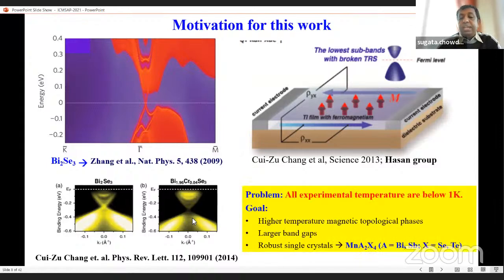The question is that all this experimental work has been done at very low temperature, and in these two cases the temperature is 1 Kelvin. If it is 1 Kelvin, practical application is really tough. So for a useful practical application, we need a higher operating temperature which shows this kind of property. Second, we need a larger band gap, and third, a robust single crystal. So that was the development going on.